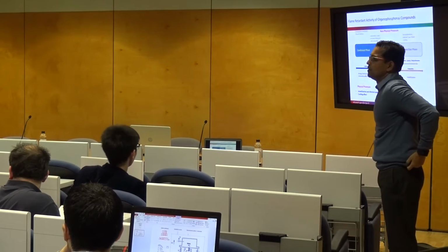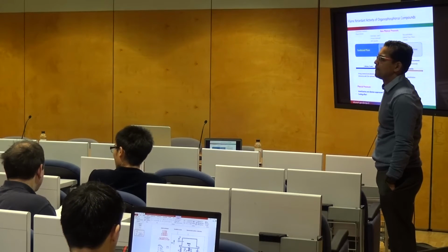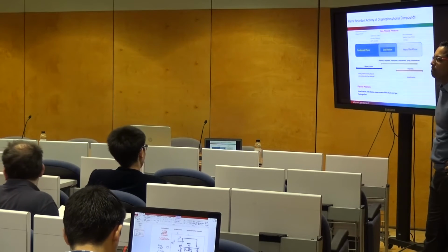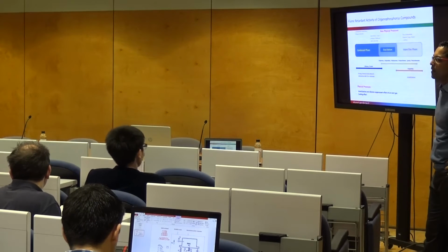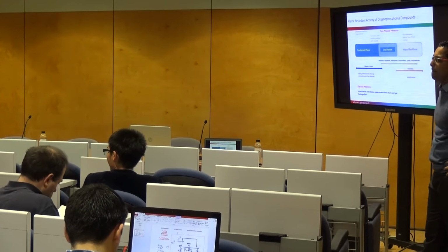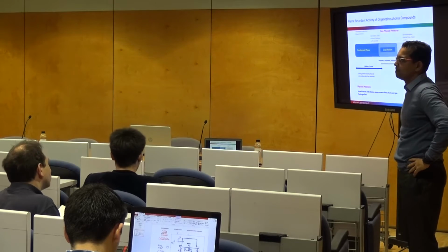Just a remark about dripping. In some investigations, it should be interesting to analyze the drips, because it can give some information about the mechanism of fire retardancy and also the way of decomposition of the polymer, because there is oxidation, but there is also chain breaking, and for polyesters it is very important to take into account different mechanisms of degradation.